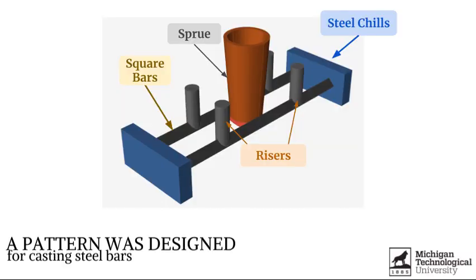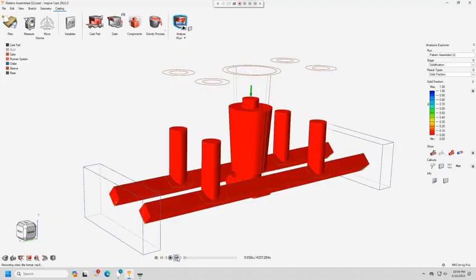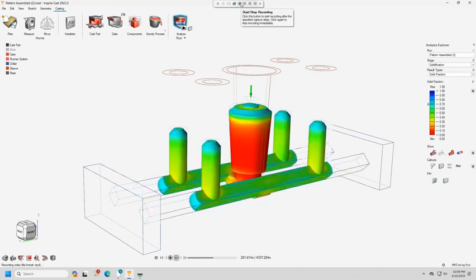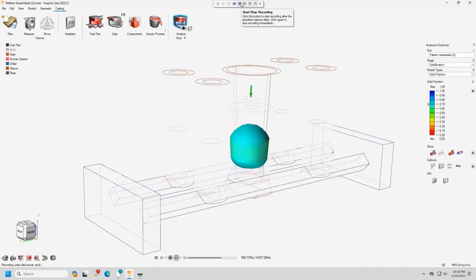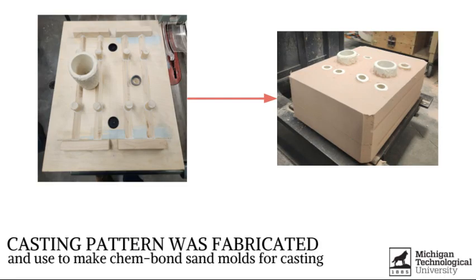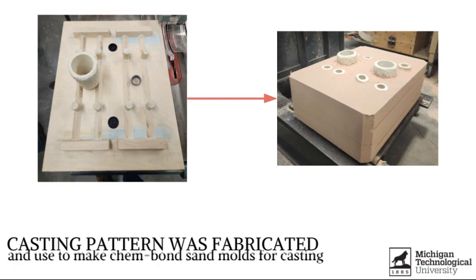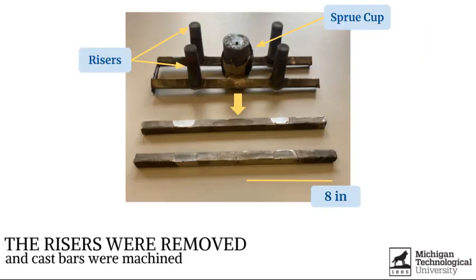To start off, we needed to design a pattern for casting. This is so we could make 16-inch bars with 3/4 inch cross-sectional side lengths. Inspire Cast, a casting simulation software, was used to ensure our bars would be free of porosity and cold shuts and would have proper cooling. The design pattern was then used to make chem-bond sand molds. They were designed to make a total of 4 bars per mold. Once cast, the sprue cups and risers were removed and the bars were machined down.